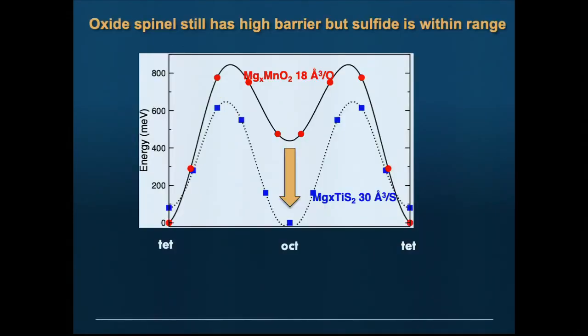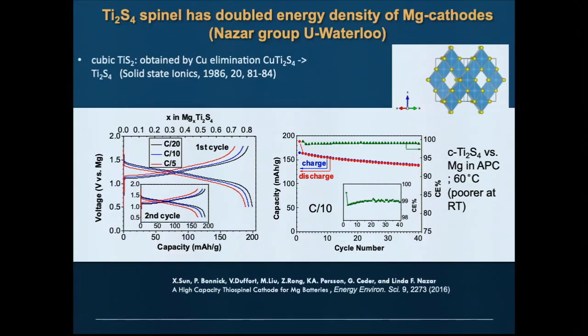Okay, so if you calculate that with an oxide, this is the migration path. It's still pretty high, about 800, 850 meV, which is still too high to do at room temperature. But if you get a little help from your friends, the anions, and you go to a sulfide spinel, because of screening, you can bring this down to 600 meV, which is not quite like lithium ion, but that actually works. This is work we did with Linda Nazar as part of JCESR. If you take a titanium sulfide spinel, which you make by making a copper titanium sulfide one and leaching out the copper, you can actually cycle this at very high capacity. This is comparable capacity to lithium ion, 200 milliamp hours per gram.